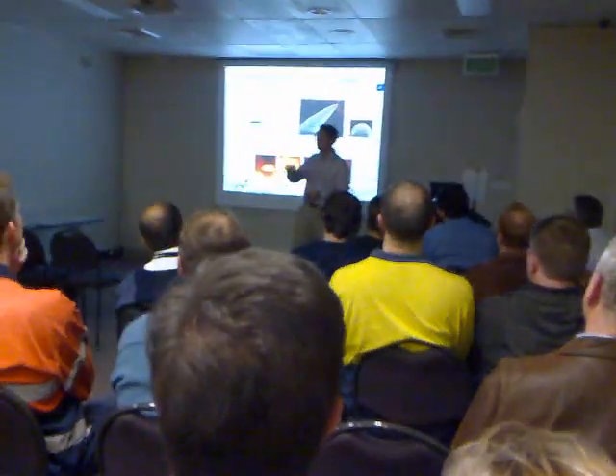What this does is we essentially take a very fine optical fiber that's bent down to a corner, and at the end of it there's a tiny hole — this one's about 500 nanometers, but we can buy them off the shelf down to about 50 nanometers. So we create a little torch that we can move across our circuit. The tip also has another laser, so we send laser light down through the fiber optic. We have another laser on top that bounces off the tip and we can measure exactly where the tip is. We turn it into an atomic force microscope.